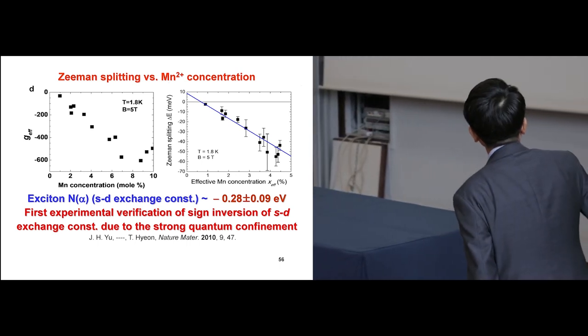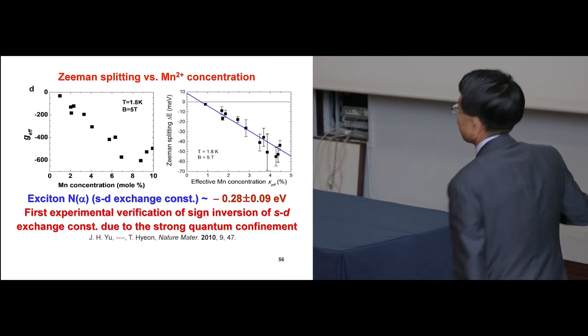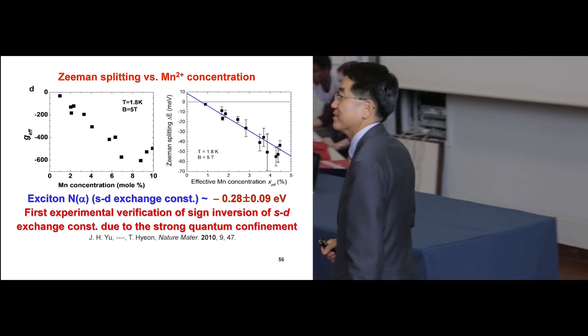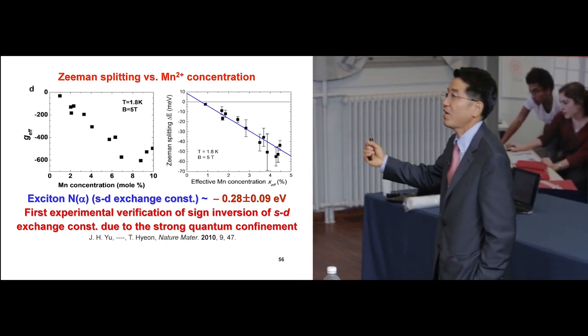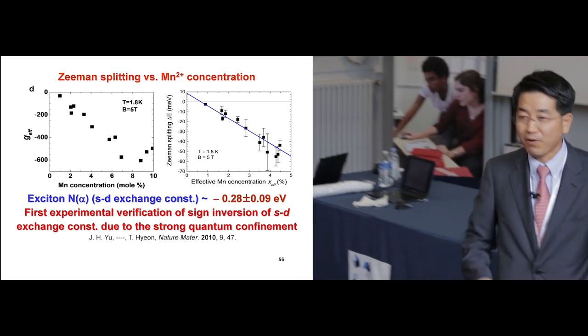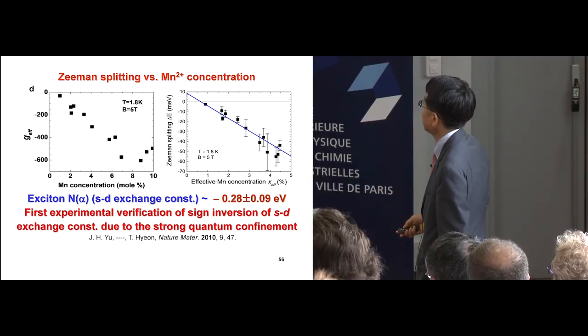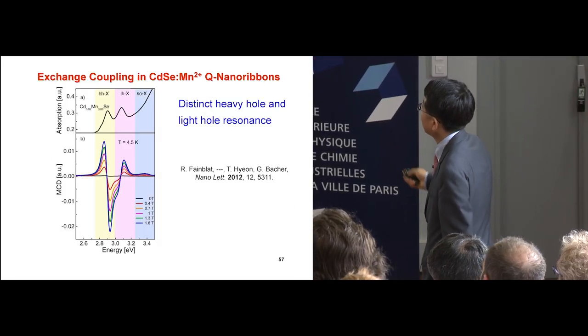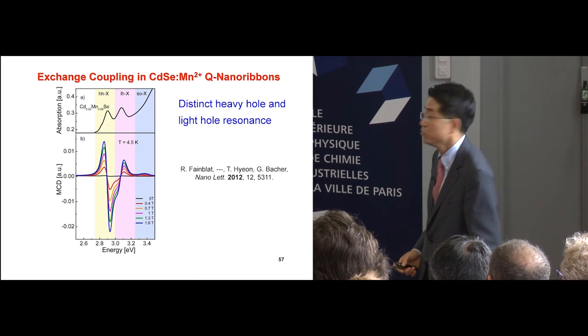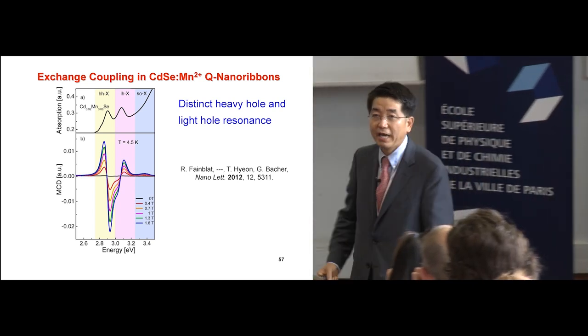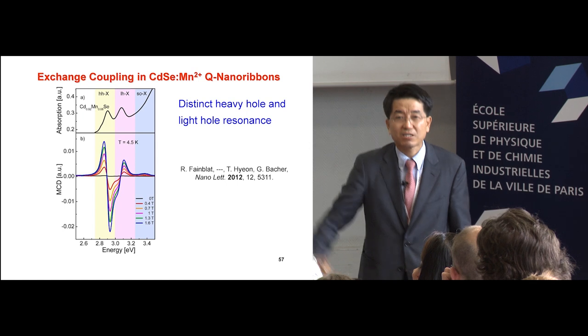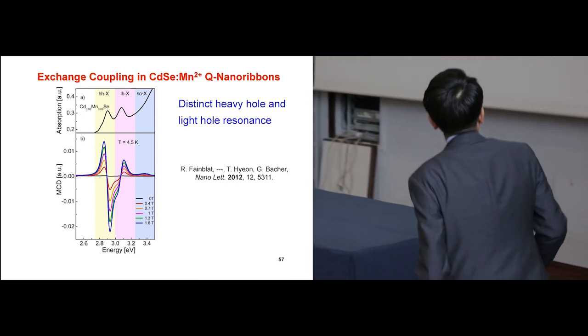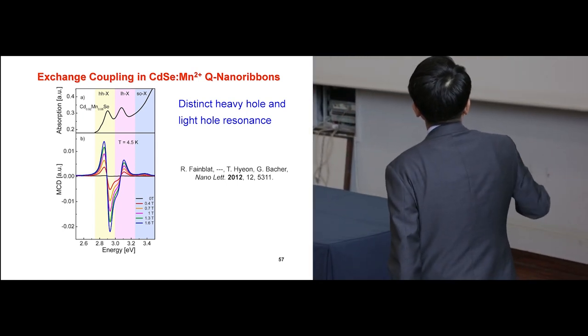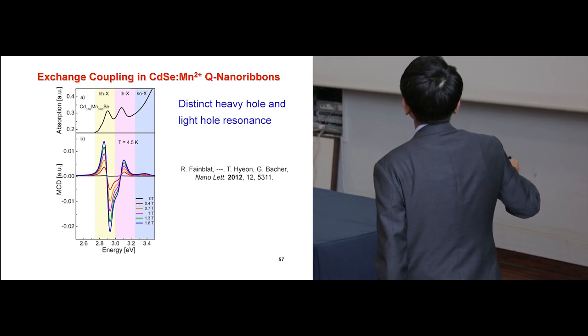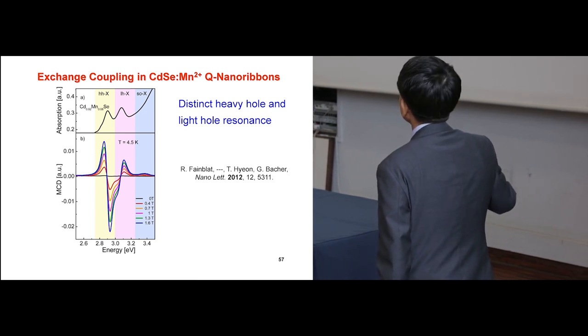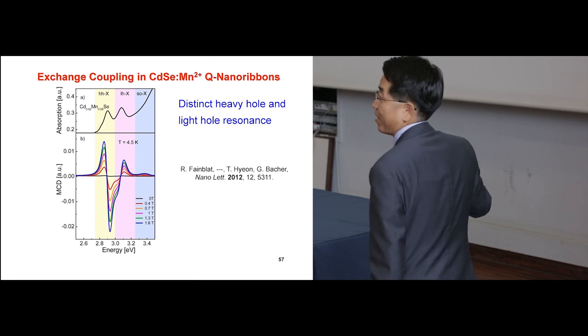And that's exactly what you observe, because we could vary the concentration of manganese and characterize the magnetic properties. That's what was reported in Nature Materials a couple of years ago. Later, the Gerd Bacher group in Germany picked up our materials and looked at more details like magnetic structures. And as you can see, the distinct heavy hole and light hole bands can be clearly resolved here.